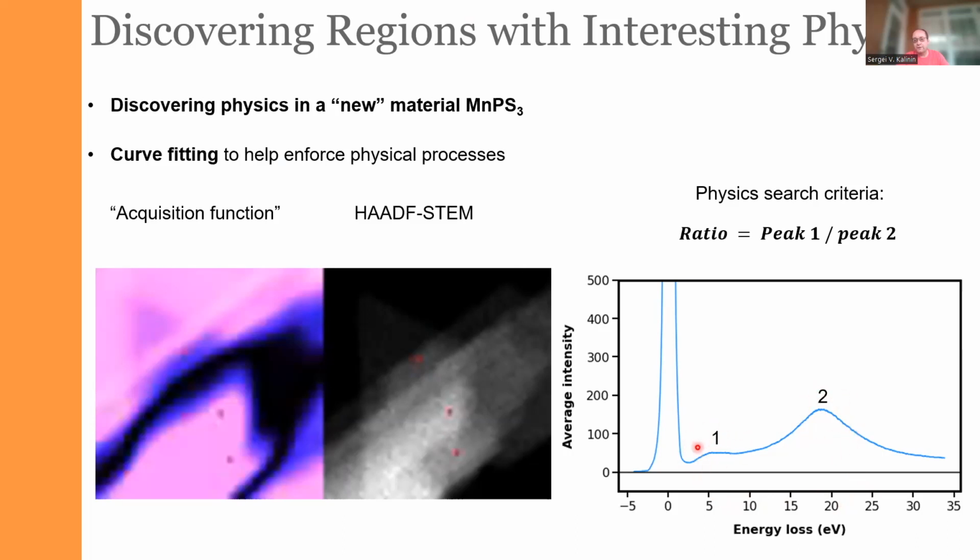This peak corresponds to the surface plasmon, or presumably the bulk plasmon. So what we can do is define the workflow where we start with the EELS spectrum, cut off the zero loss part, fit the remaining part of the spectrum with two peaks with approximately known positions, and then we take the ratio of these two peaks and we use it as a scalarizer.